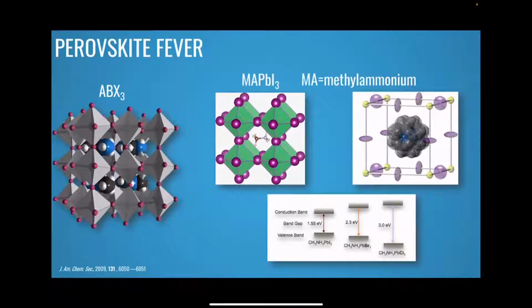Anyway, in 2009, this perovskite, methylammonium lead iodide, CH3NH3PbI3, you see the classical perovskite structure, but here there is a halide as an anion. Many of us may be aware of oxide perovskites. Anyway, this perovskite is called a hybrid organic-inorganic, because on the A side of the perovskite, you have an organic cation, methylammonium, and then we have lead. This is a semiconductor. The band gap is around 1.55 electron volt.